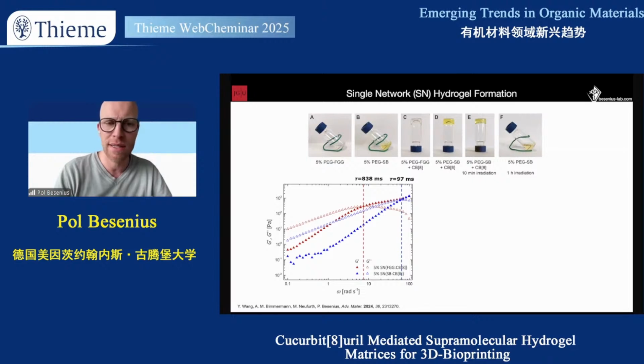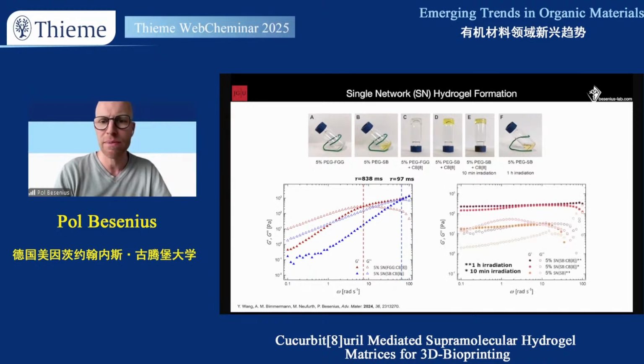For the stilbazolium unit, it's kinetically a little bit more robust by about an order of magnitude. If you then shine light on this material, then the rheological behavior changes completely. In the dark reddish colors, what you start to see is that there's a plateau value over the whole frequency range that we examined here, at least, and this really tells you that you go from a material that is viscous to a more solid-like property, and this happens more efficiently if CB8 is present in